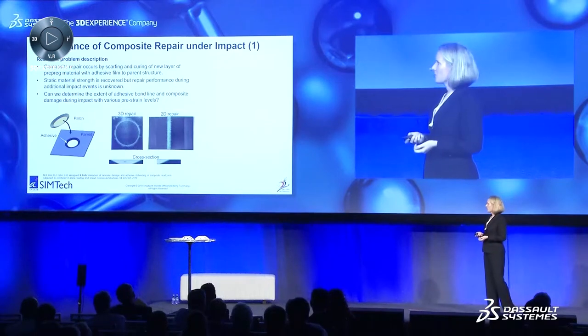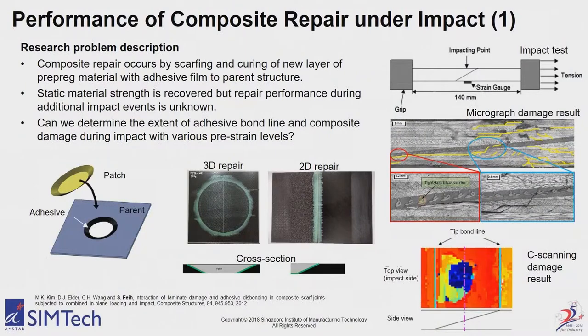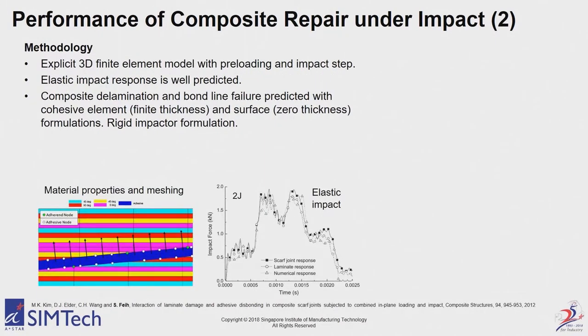And is the adhesive layer prone to damage in that case? What happens with the interaction of composite and adhesive damage? How can we actually characterize that? And so we did quite a few impact tests on our scarfed bond line, and we did a lot of experimental studies and C-scanning studies to study the failure that occurred. And we could see a lot of delamination between the plies, and of course we were planning to actually validate this numerically. And so we created a model in 3D that had all the relevant parts in it.